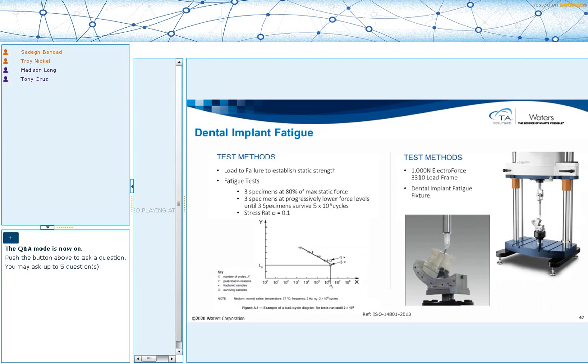So this is a good comeback to the first slide that we discussed on how you correlate the quasi-static behavior with cyclic fatigue behavior. It says pull a sample to measure its ultimate tensile strength. So break the sample to establish the static strength. Now start at 80% of that to create your fatigue graph, SN curve. Start at 80% of that maximum static force, test 3 samples, and then progressively lower that stress or force level until you get 3 samples that survive 5 million cycles.